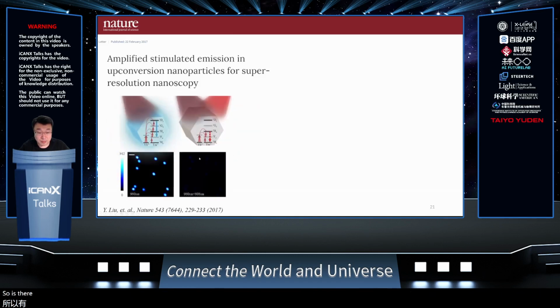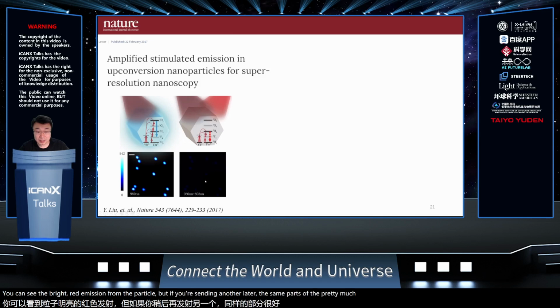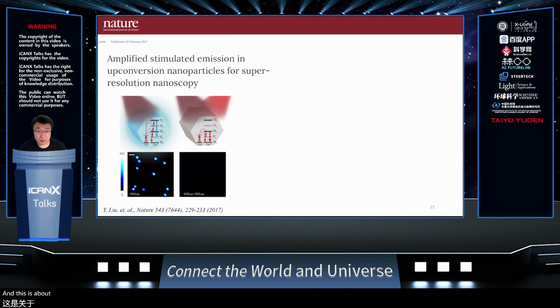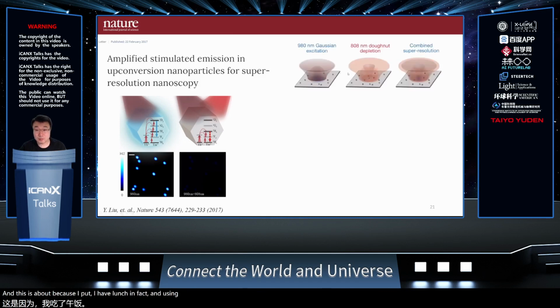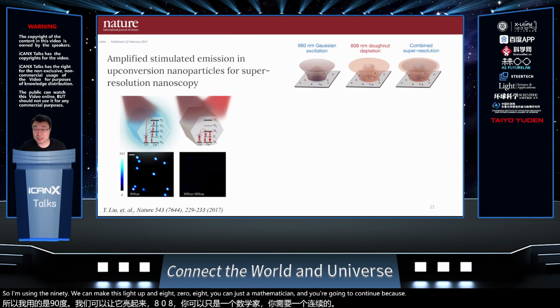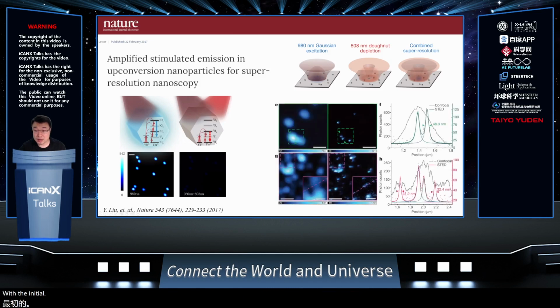Experimentally, what you see is that if you shine one laser, a 980 laser, you see bright emission from the particle. But if you shine another laser at the same time, it pretty much switches this emission off. This is because of the photon avalanche effect. Using this, we can build a STED experiment. Using the 980, we make the particle light up, and with the 808 you can make the depletion. And here you can use a continuous beam, because you really just switch the emission off. Using that, they achieved 30 nanometers.